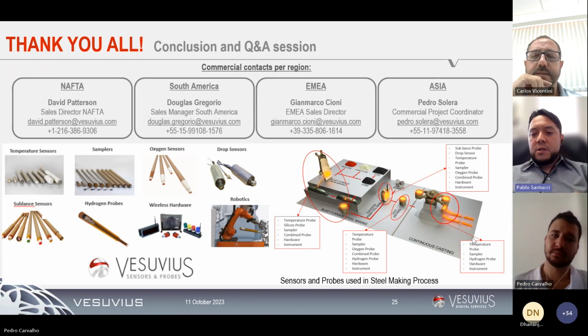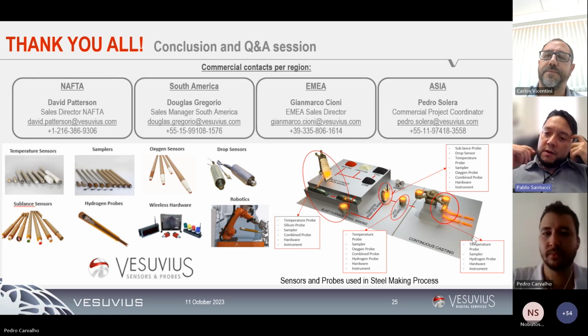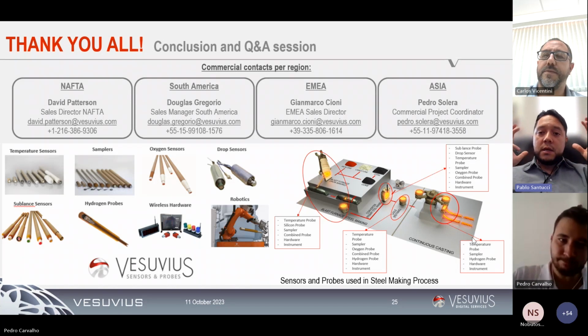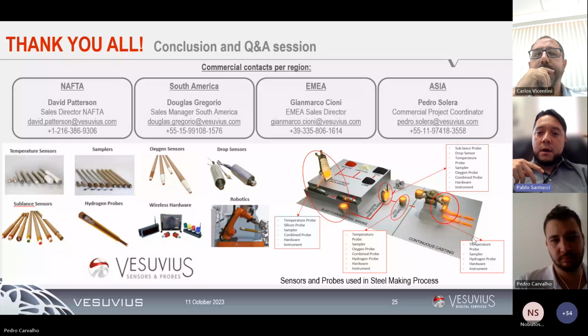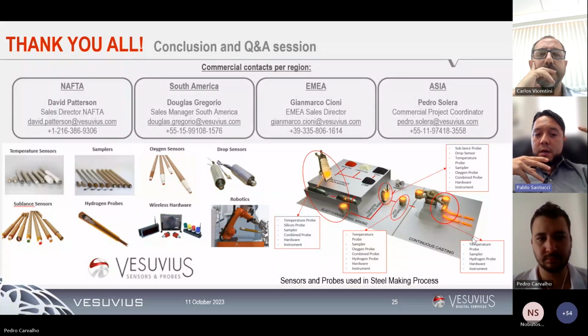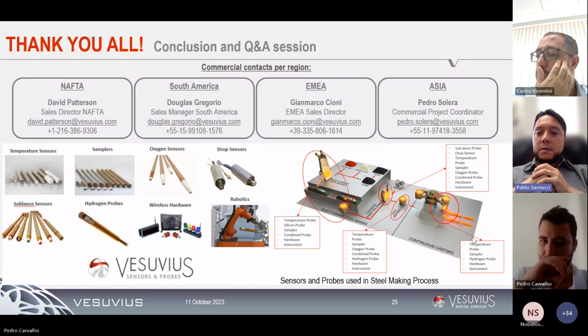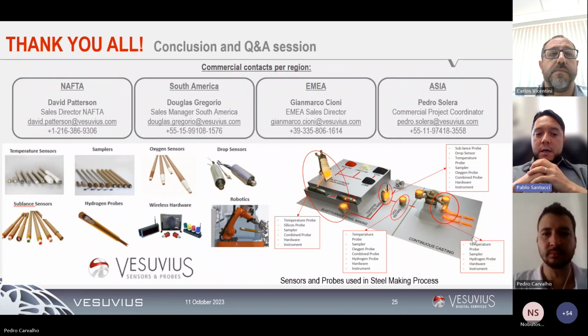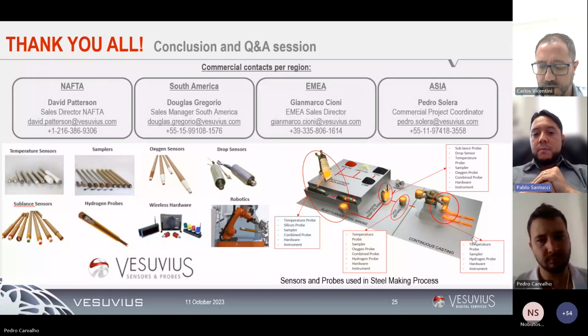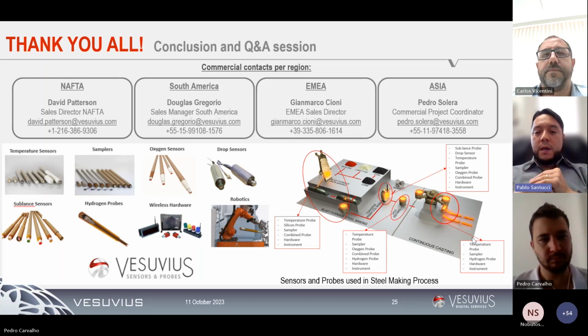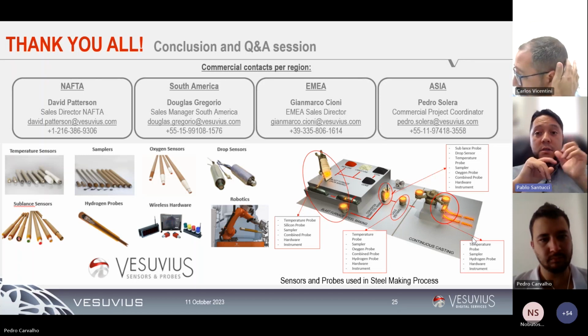The answer is yes, it's possible, because the thermal conductivity of argon is very similar, but once again, not the same in comparison to nitrogen. Both of them, argon and nitrogen, have a thermal conductivity very different from that of hydrogen. So that being said, argon can be used. However, our system has been calibrated at our manufacturing site using nitrogen. So every time a request like that comes, we need to recalibrate our system based on argon, and use argon as the carrier gas for this specific unit.